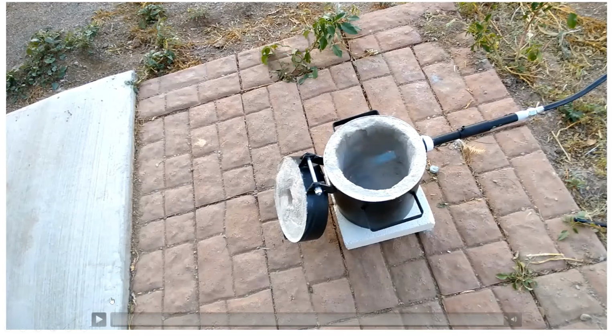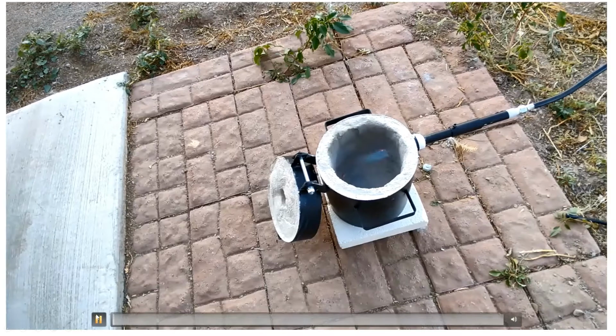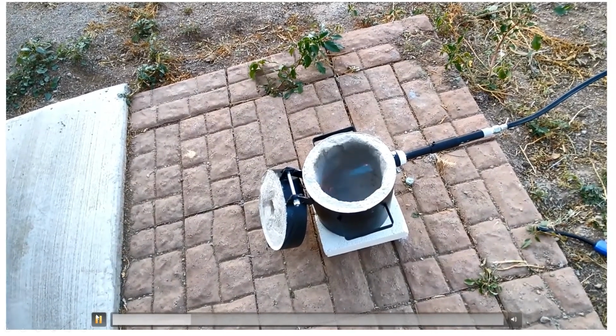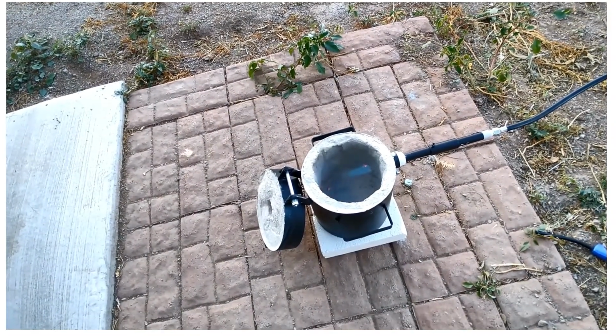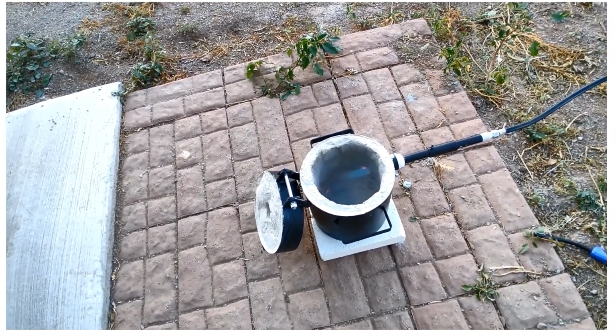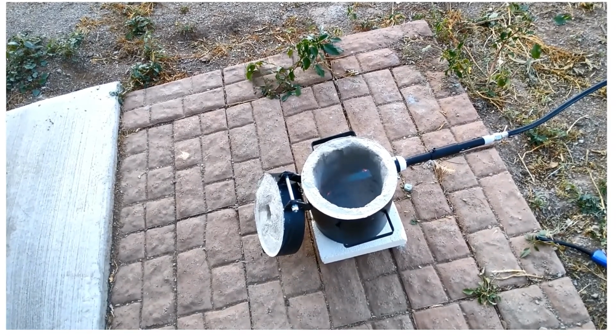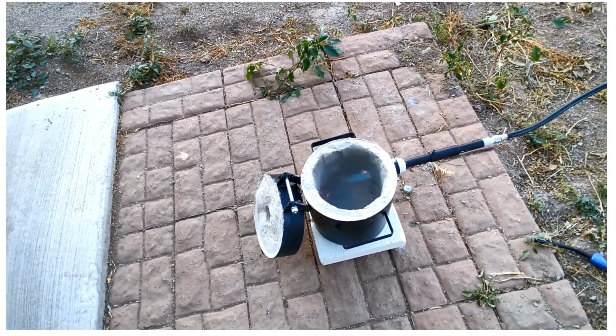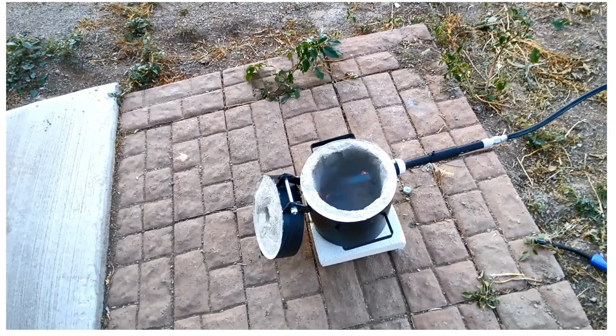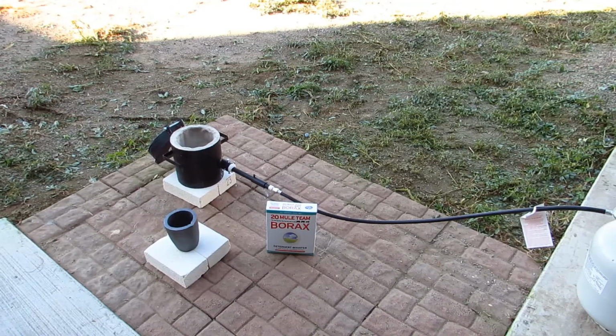I then subjected the furnace to a test run, and it was pretty cool. You had a nice blue flame, and it sounded like a jet engine, and that's pretty much what you want. I let the furnace run for about 5 minutes with the lid closed, and then I turned it off. This was to make sure all of the moisture was baked out of the furnace, so I wouldn't have any problems with gas trying to evolve from the furnace.